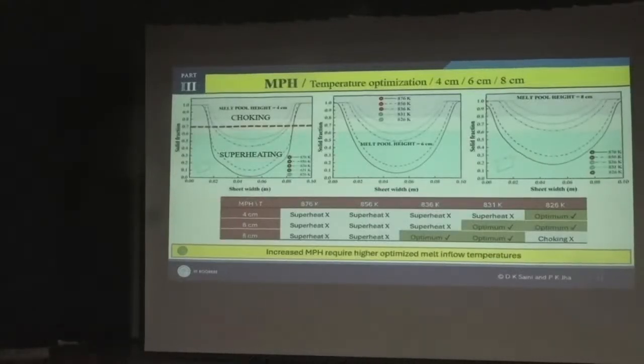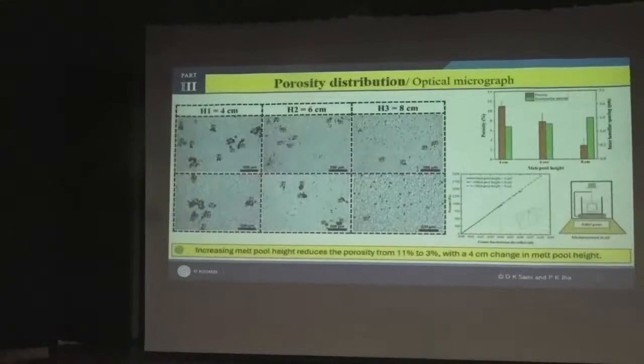So ultimately we did this with the melt pool height, and we got a few results with that also. We saw how we are getting with what melt pool height, and how you need to adjust your melting point or the pouring temperature of the metal, so that you get an optimized sheet. These are some of the intermediate results.